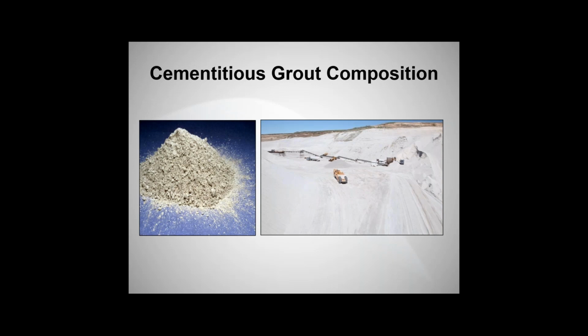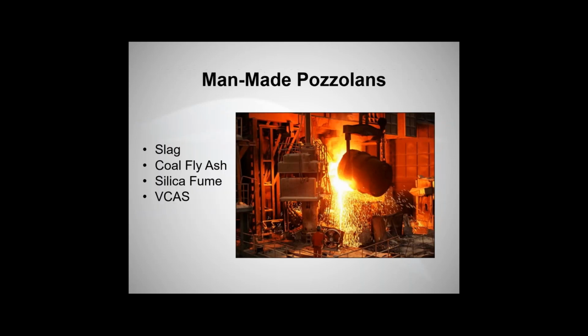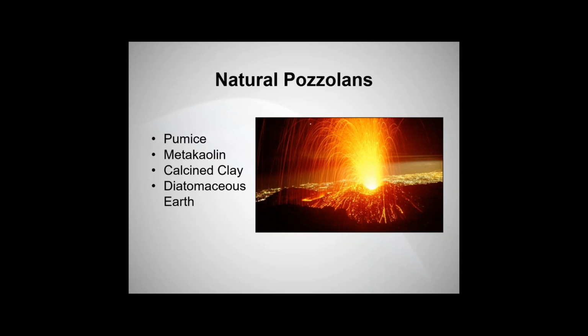So what comprises an ultrafine cement? Well, it's actually just Portland cement and some type of pozzolan. The type of pozzolan that is typically used is slag. Slag is the predominant man-made pozzolan, and it's a byproduct of the steel manufacturing process. There are also coal ash, silica fume, and VCAS, but slag is really the predominant one. There are also natural pozzolans, and the predominant one used is pumice. Metakaolin, calcined clays, and diatomaceous earth could be used as well, but predominantly it's pumice.